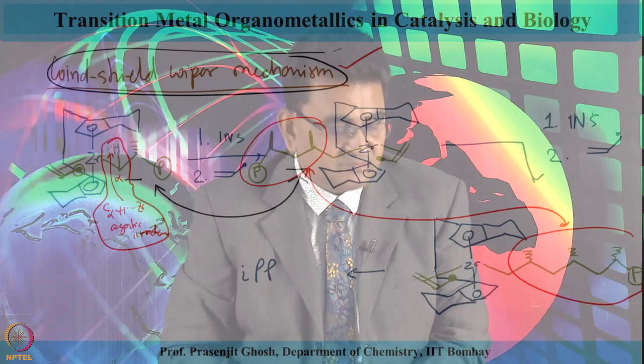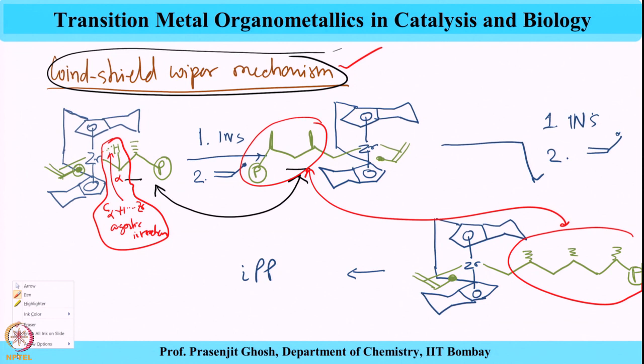With this, we have seen how the single-site homogeneous catalyst gives polypropylene of high stereospecificity, and how symmetry plays a great role in distinguishing between the faces of propylene — the alpha olefin that approaches — resulting in a highly regular stereoregular structure producing isotactic polypropylene. We have also seen the role of the ANSA ligand, the bridging ligand, and how it helps in opening up the cyclopentadienyl ring for better approach of the polymer chain and the catalysis. This is a very nice demonstration of good thinking in chemistry and how it can lead to catalyst improvement.